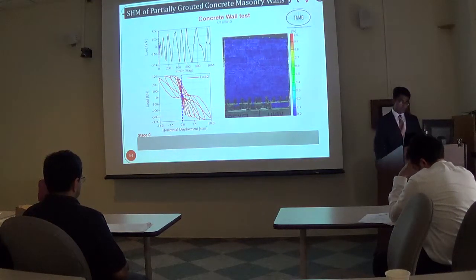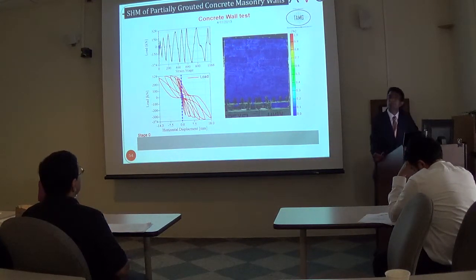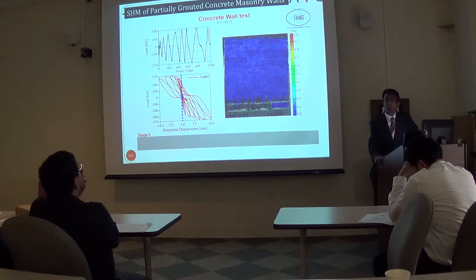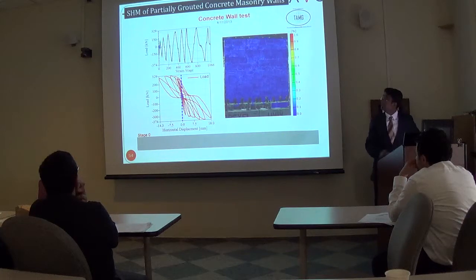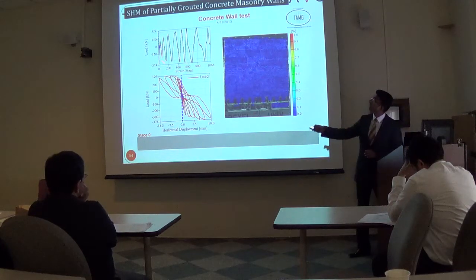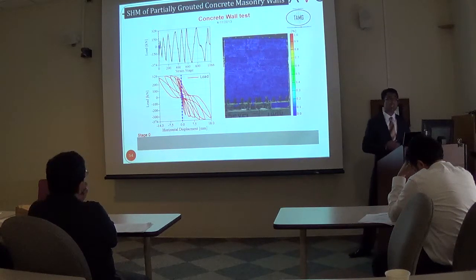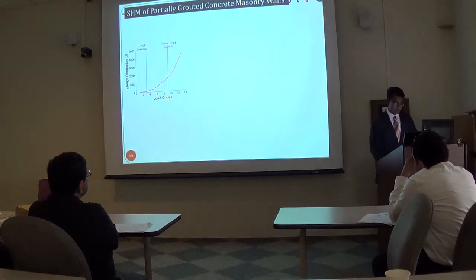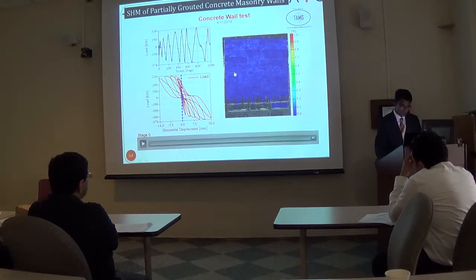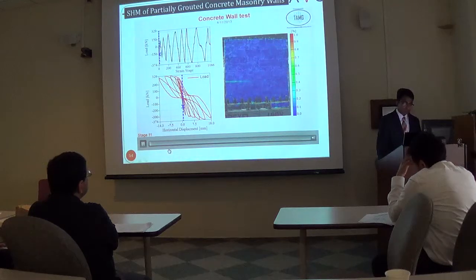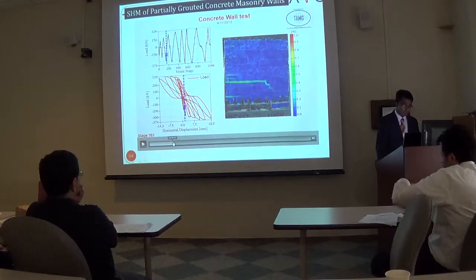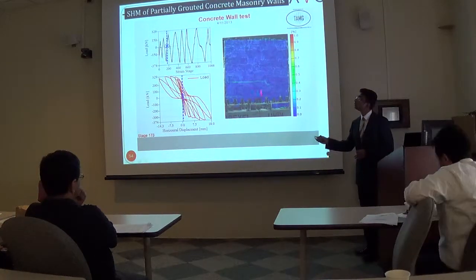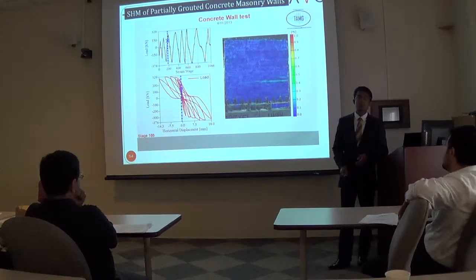So I'm going to show an interesting video of how the DIC picks up early indications of strain accumulation much before we can visually identify any cracks in the specimen under the different loadings. As the wall is being loaded under tension and compression, you can see how the strain accumulates in the medium. As the wall is being loaded, you can start to see how strain accumulation picks up in specific regions of the wall. And at this point, we still